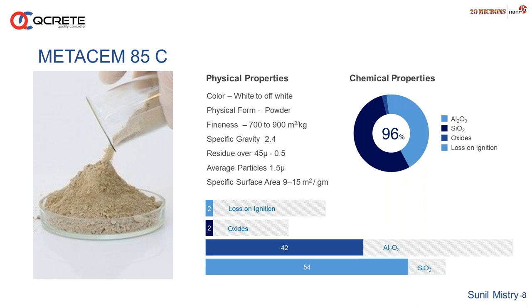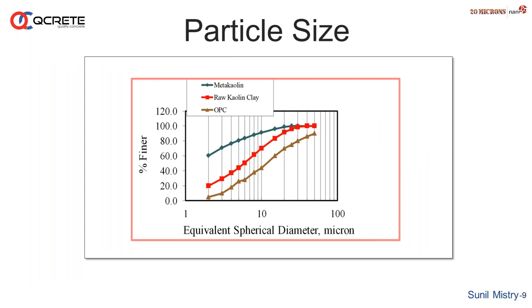On your right side, you can see this 96 is the total reactive compound in it. So it contributes silica at 54-55%, whereas alumina is 40-42%. So in total, this mineral admixture, metakaolin, contains 96-97% reactive compound. That's why the literature says it is the highest among the reactive mineral admixtures available in the industry.